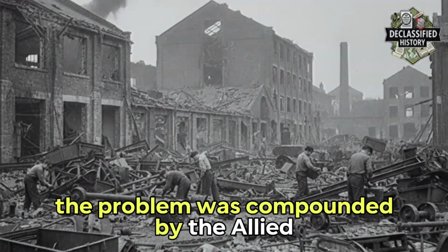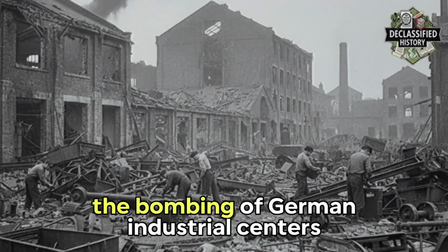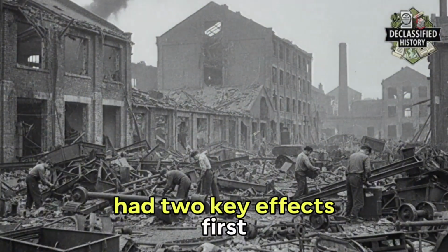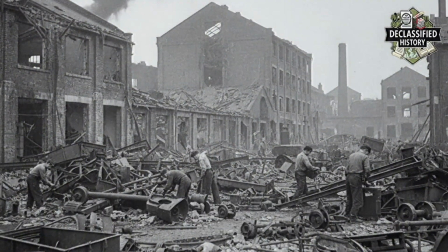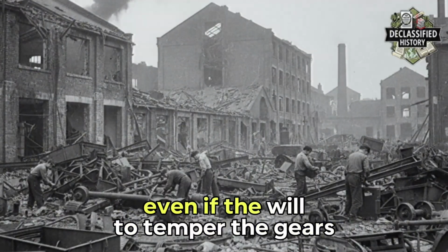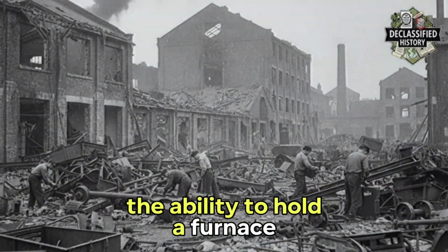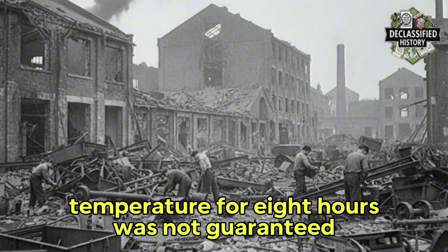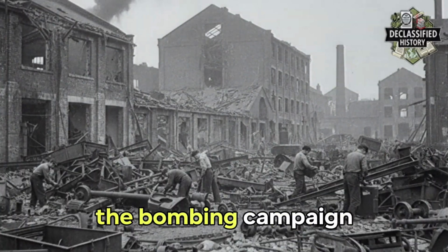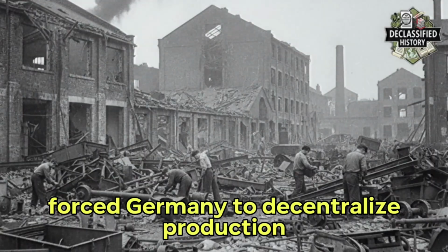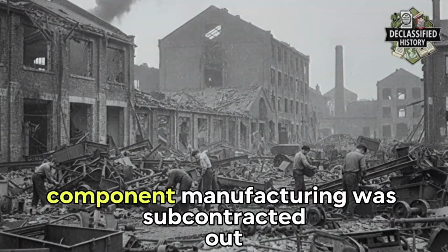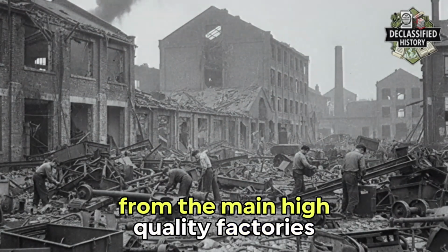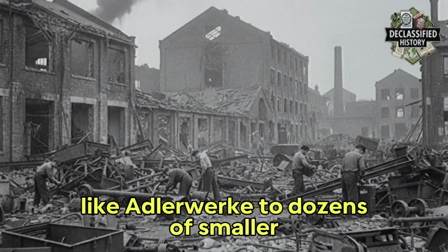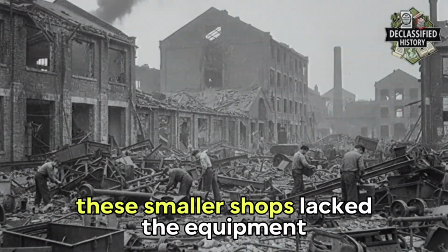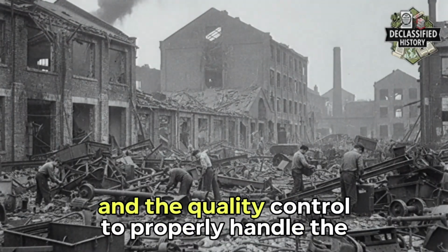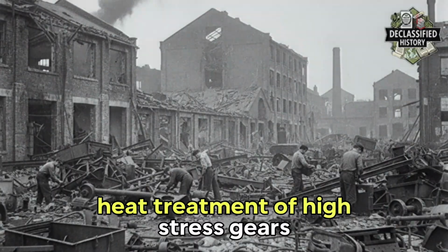The problem was compounded by the Allied strategic bombing campaign. The bombing of German industrial centers had two key effects. First, it directly hampered quality control. Power cuts and damage to facilities meant that even if the will to temper the gears existed, the ability to hold a furnace at a precise temperature for 8 hours was not guaranteed. Second, and more importantly, the bombing campaign forced Germany to decentralize production. To protect against single-point failures, component manufacturing was subcontracted out from the main high-quality factories like Adlerwerke to dozens of smaller, inexperienced machine shops. These smaller shops lacked the equipment, the expertise, and the quality control to properly handle the complex heat treatment of high-stress gears.